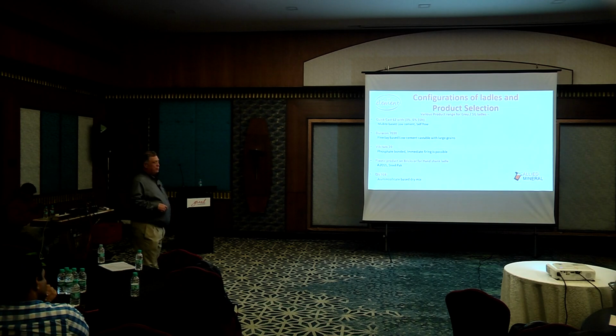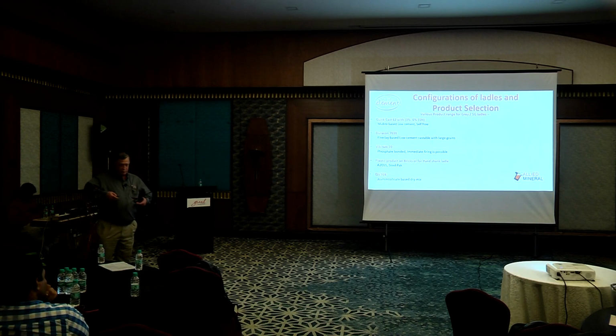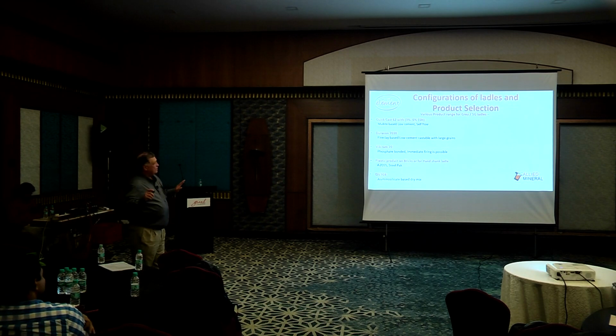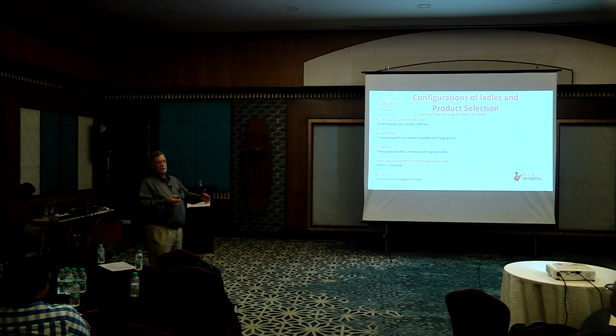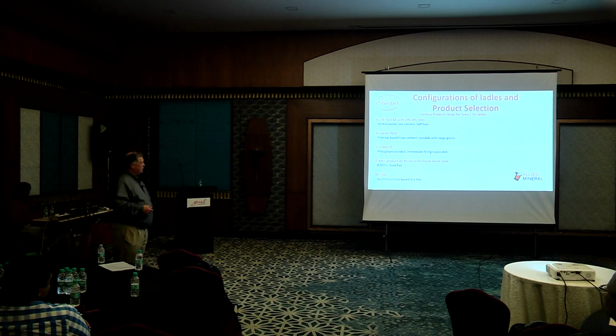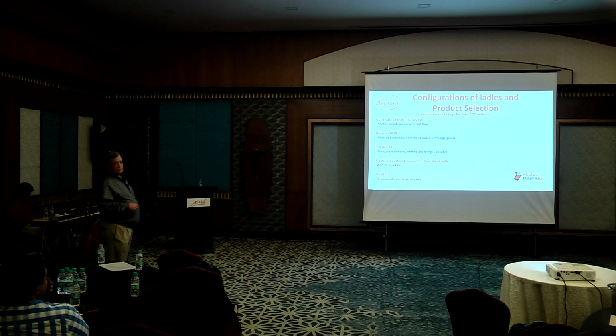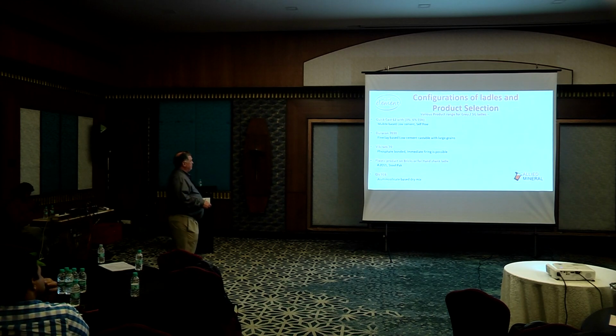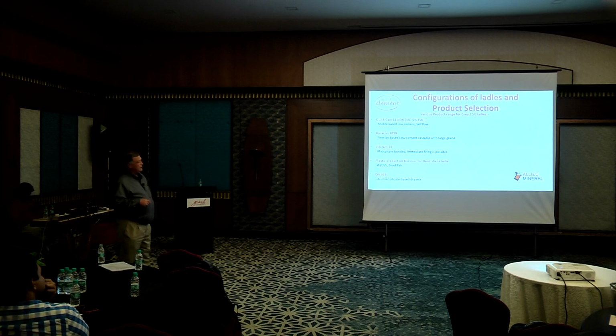Again, we talked about Vibram. That's a vibratable plastic. It comes in like baggies, and you pour it like you're pouring dry vibe, but it's got moisture. When you hit it with vibration, that moisture releases very quickly, and it flows like a castable. But you don't have to have a pencil vibrator. You just need a shell vibrator or a mold vibrator, anything like that. So most foundries have it available. And then, of course, you have plastics. These can be hand rammed. Phosphoric acid plastics are probably the best to use. There are phos-free plastics as well. And then DV, which is 916. It's an aluminosilicate-based, fire clay-based, dry vibratable material for ladles.